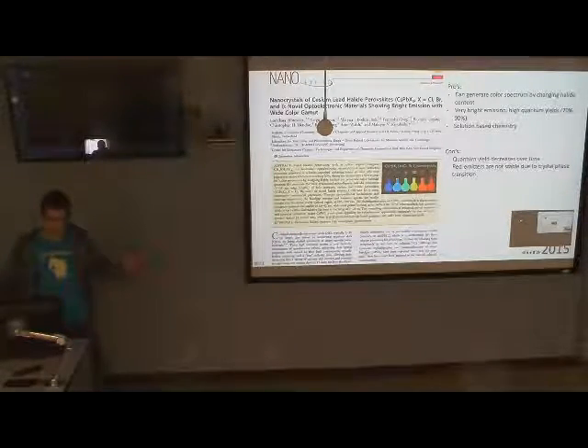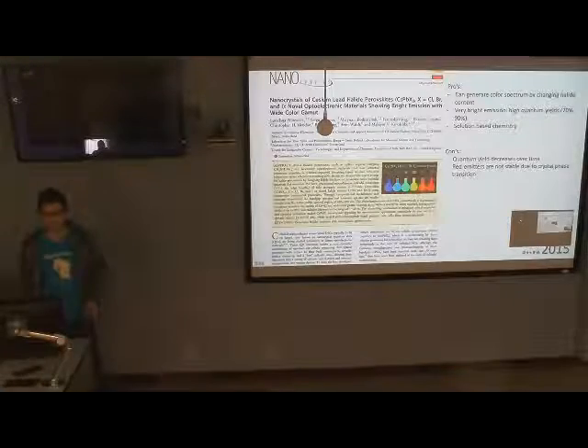So anyway, the impressive part with this is they can generate the entire color spectrum, which is handy for materials applications because, I don't know, white light is pleasant. They can generate different colors because they change them primarily by changing the halide content in the perovskite crystals. In CdSe, those are changed based on size. There are some size effects here too, but they're second order compared to just changing the halide content. So it's easy to generate different colors, you just have to put in different chemicals.